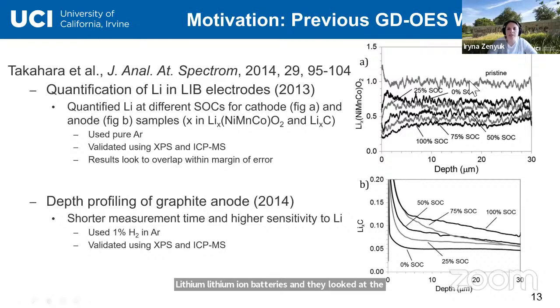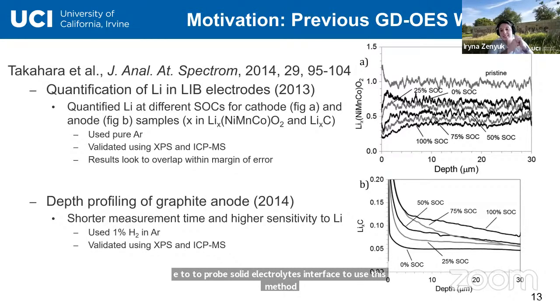You can see here, this is the pristine electrode, and this is going from 0 state of charge all the way to 100% state of charge. They also did the same thing for NMC and for the carbon anodes as well. What's interesting, this is a group that is really active in this field, and you can see that the profiles are really well resolved, and we can see these local fluctuations as well, and we can also detect things that happen at the interface. This is the most interesting phenomenon, because if we are to probe the solid electrolyte interface with this method, we really need that nanometer resolution.